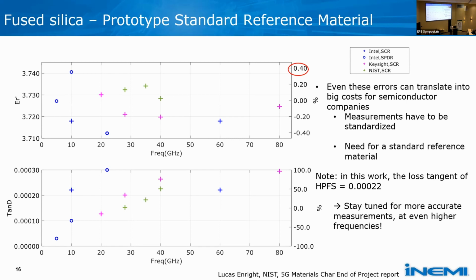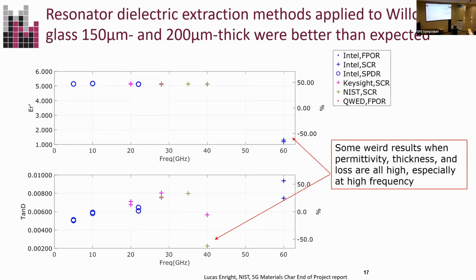One of the things to notice is that even with the scatter, we're looking at a 60 gigahertz measurement out here that's looking even better than what I quoted before for high purity fused silica. So this is really a very nice low loss material. And I think out of this project, once there's a reference, we're going to get even nicer measurements.